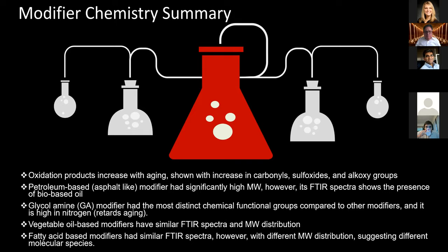Vegetable oil-based modifiers have similar FTIR spectra and molecular weight distribution. The fatty acid-based modifiers had similar FTIR spectra, but they had different molecular weight distribution, which gives you an indication that they were different molecular species, even though generically classified as fatty acids.